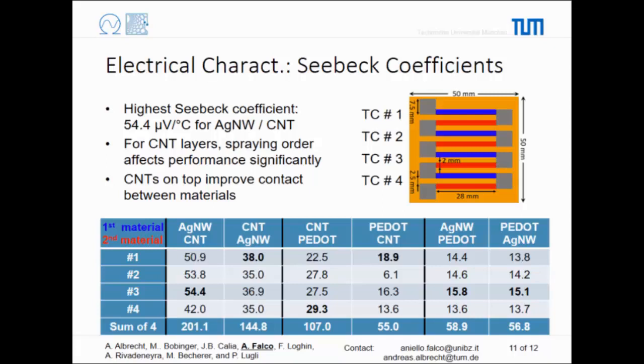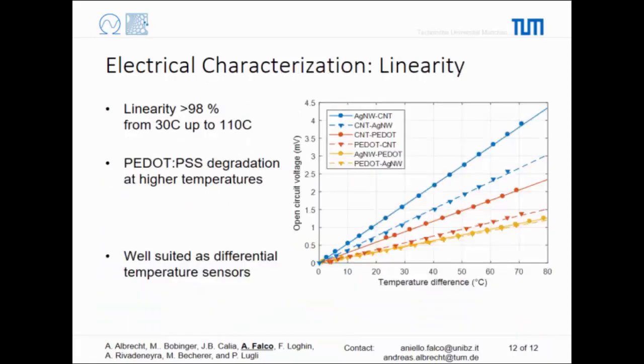Concerning a measurement against temperature, you can see it in the next slide, and we'll show that as a differential temperature sensor, it is quite linear. Regardless of the couple of materials that we decide to use, it works fairly well. Concerning the sensitivity, we're speaking of 50 microvolts per Kelvin, which is pretty decent, and linearity is above 98% until 110 degrees. I did not present the plot beyond 110 degrees because, as I was saying, the PEDOT PSS would stop functioning, so that would not be a fair comparison. But for sure, you can see that the silver nanowire carbon nanotubes couple, regardless of the combination order, are the top performers here.